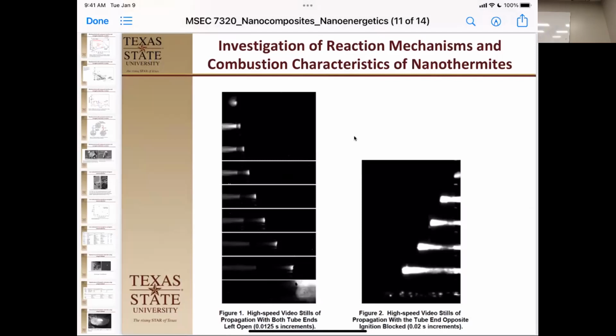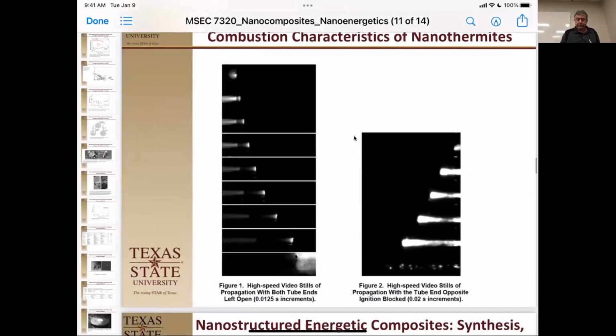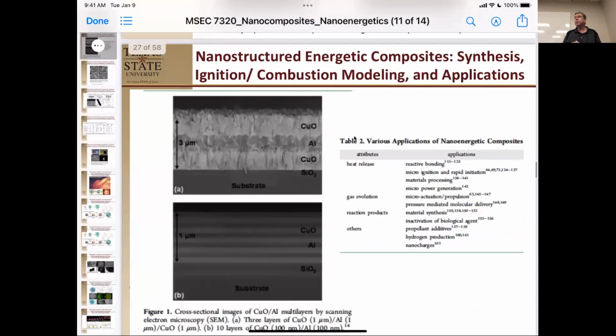So at this point right here, it's actually burned all the way out the tube, and this is just residual material. Okay, so again, it's creating its own gases as it's burning. It's having to burn through the material as it's continuing until it gets to the low pressure zone. So you see a different burn. See how there's much more burning taking place at the closed end of the pipe until it actually gets out into the pipe. So by measuring these high-speed things, we can actually look for that. Okay, so that's one way to do it.